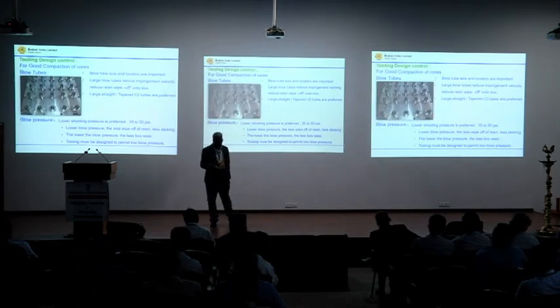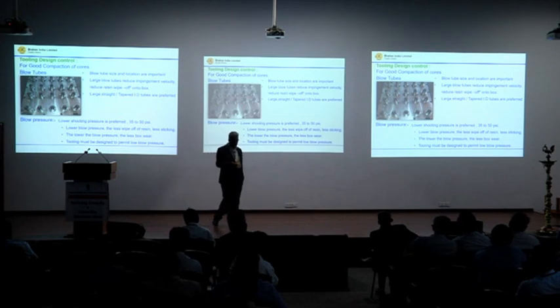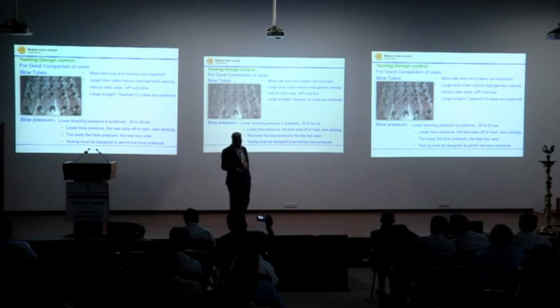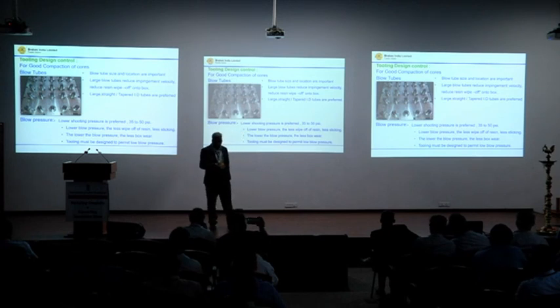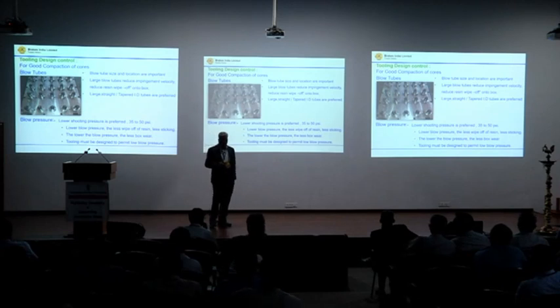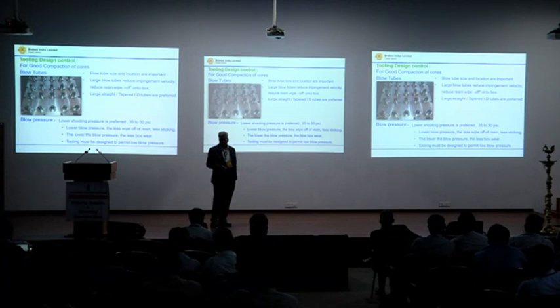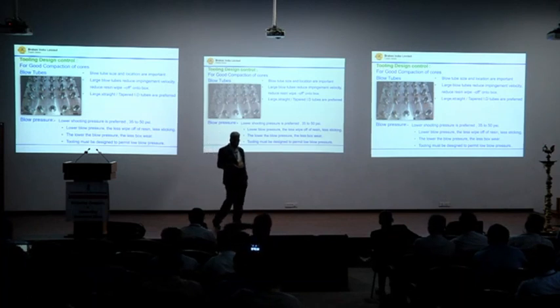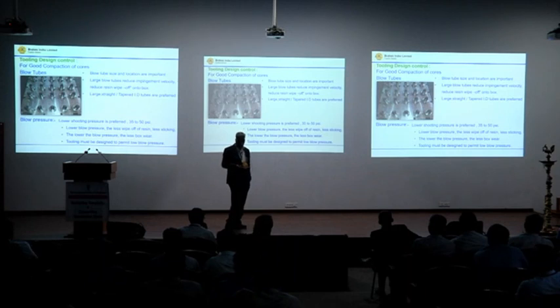This is the blow tube design for getting well compacted cores. Blow tube size and location are very important. Large blow tubes reduce the impingement velocity of the sand, reducing wipe off and deposit on the core box. Large, straight, and tapered ID tubes are preferred.